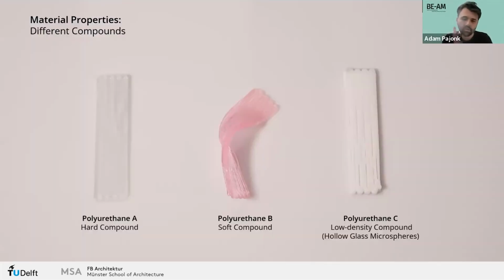And now, while first initial tests were done with just different colored materials, we then looked into a set of specific material properties which could be combined and used for further testing. So we defined a hard compound, a soft compound, and in addition to this, also a compound which represents a very low density compound, which is in this case created with hollow glass microspheres.